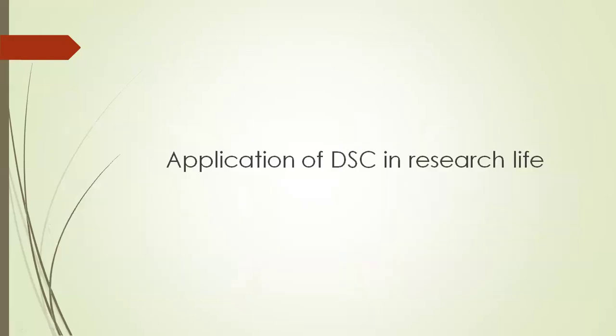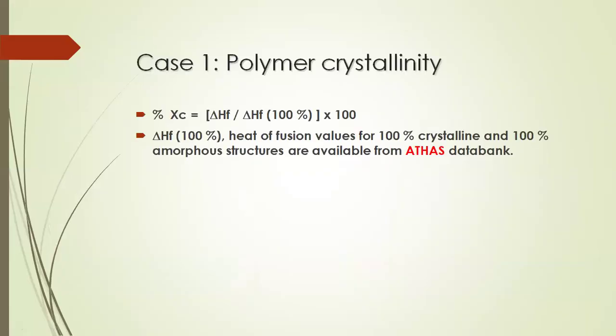DSC can be used extensively in research because crystallization kinetics can be studied using DSC. You can find out the polymer crystallinity. You can record delta HF using the DSC heating curve, and you can find out delta HF of 100% pure crystalline polymer. The ratio of that gives you the calculation of percent crystallinity, which is a very, very important parameter